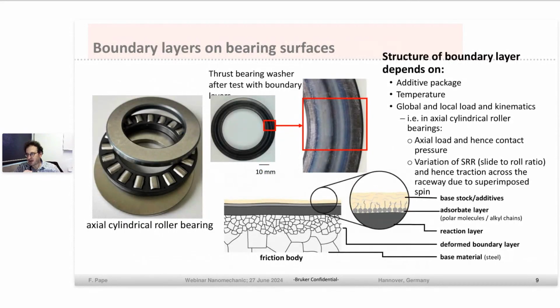Back to our bearing washer. Here on the left is a fresh bearing washer that is used in our test rig, in the FE8 test rig. And after the test, we can see a very nice tribofilm on the surface in the middle of this slide. The color is slightly bluish. Some parts are slightly red.